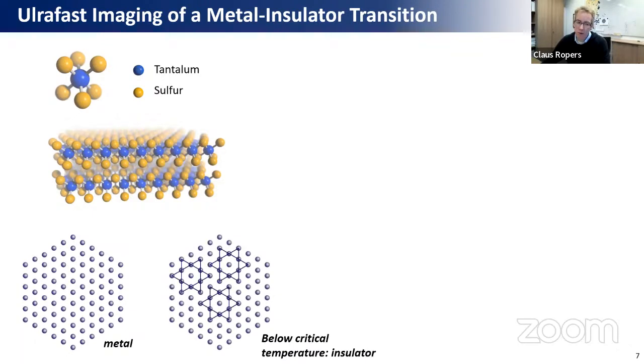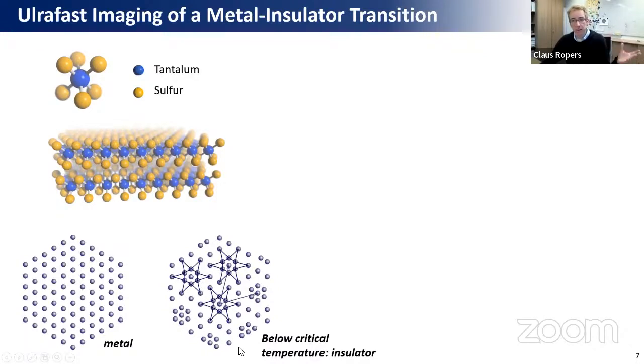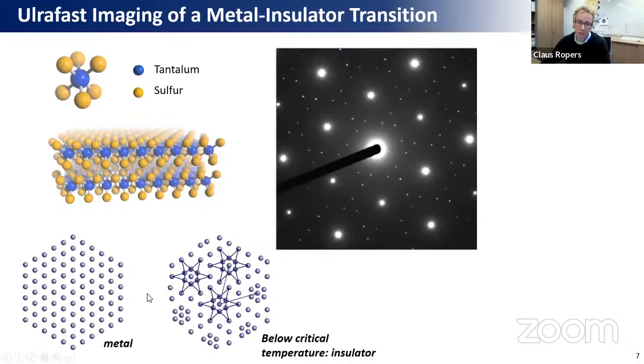But if you cool this material down to below a critical temperature, there's a transition from the high temperature metallic state to the low temperature insulating state. So it's a spontaneous breaking of translational symmetry in this material, which basically couples charge localization, so transition from metal to an insulator, with a periodic lattice distortion in a way that the atoms contract basically in a hexagram shape towards central atoms, basically forming a superstructure in this material. Yes, it's a very prominent charge density wave transition coupled to a periodic lattice distortion. In this transition, the electric conductivity changes by many orders of magnitude, actually.